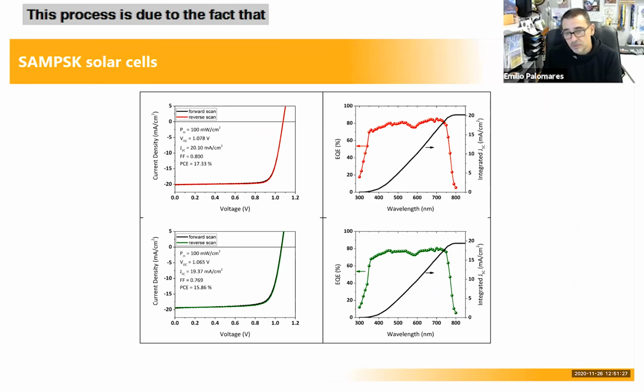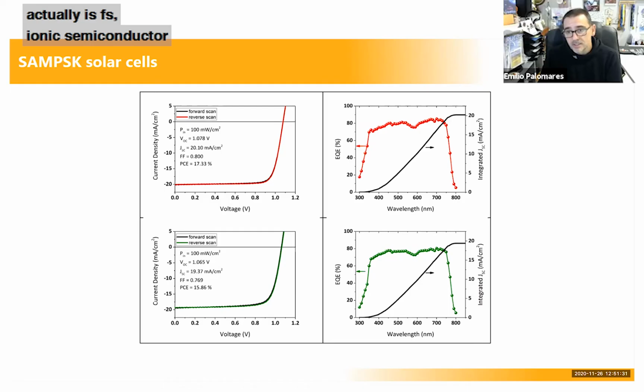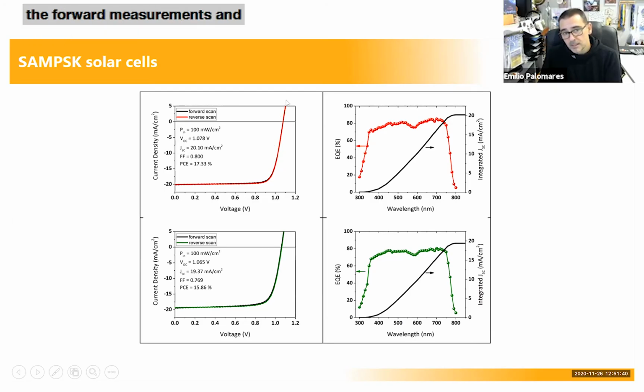This hysteresis process is due to the fact that these semiconductors are ionic. Actually, it's the first ionic semiconductor material that has been useful for solar cells. And there is a big difference between the forward measurements and the reverse measurements of the IV curve. When you use the SAMs monolayers, you don't see this hysteresis.